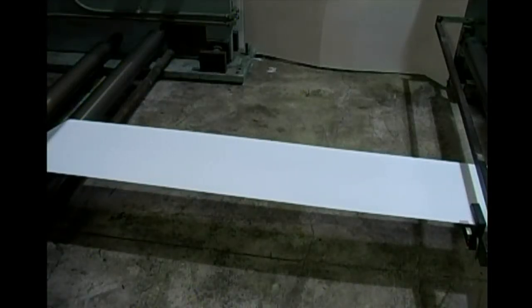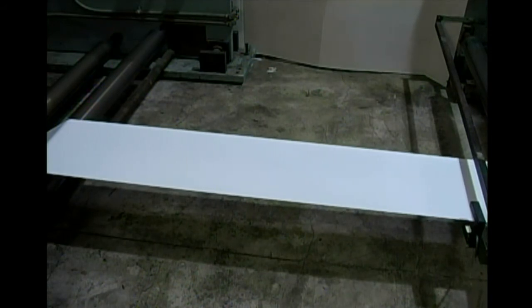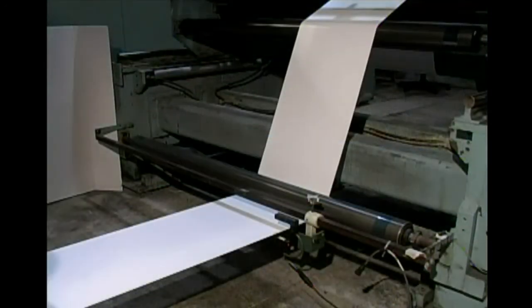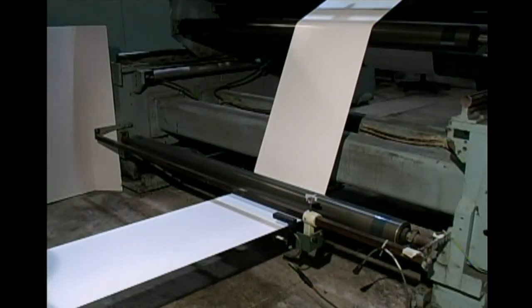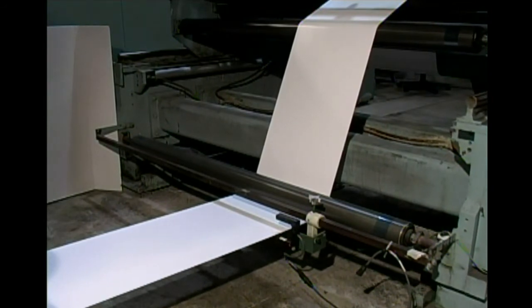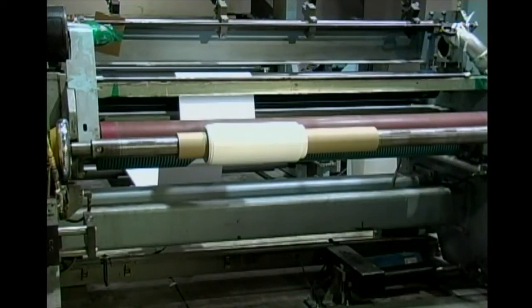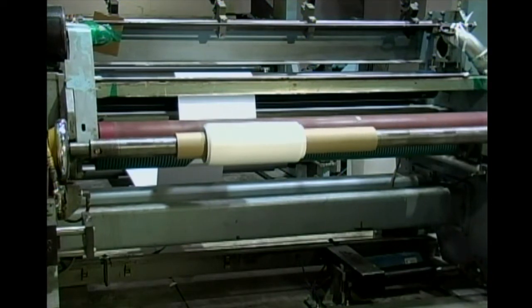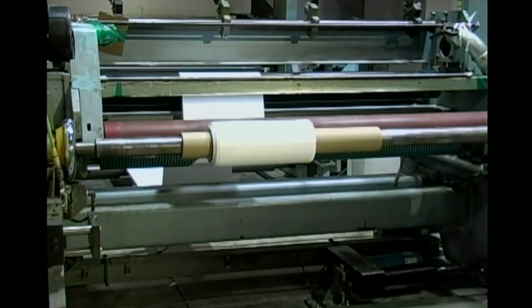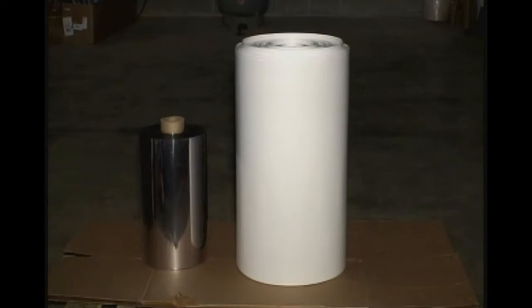As the polymer comes out of the flotation oven, it is now opaque and white because light is reflected by the bubbles in the microcellular structure. It has decreased in density while expanding about 150% in width, 150% in length, and doubling in thickness. The expanded roll will be trimmed and rewound in preparation for converting. It might now be used on a thermoforming production line, sheeted for printing and convolute forming into a cup, or perhaps an overwrap. The newly expanded PET is now twice as thick, having expanded from 20 thousandths to 40 thousandths